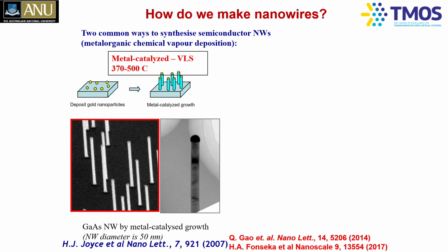Then you put this into the MOCVD reactor and, of course, introduce the gases needed for the growth of gallium arsenide, trimethyl gallium and arsine. These gases get incorporated into this liquid alloy. It gets supersaturated. Crystals start precipitating out. This is the work of my former student, Dr. Hannah Joyce, who is now an associate professor at Cambridge University.